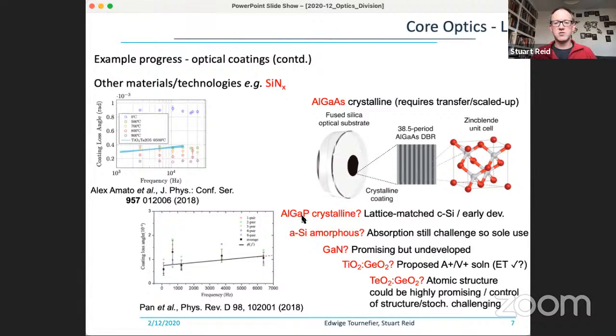There are other crystalline technologies that could be lattice matched to the test masses. Aluminium gallium phosphide would be an example of a crystalline mirror solution that could be lattice matched to crystalline silicon. Amorphous silicon is still a really attractive material, but at the moment can't be considered as the only high index material in a multi-layer structure because the absorption is too high. And there are other materials. Gallium nitride looks very promising, but it's underexplored. But within both the Virgo and the LIGO collaborations, this material is on our to-do list.